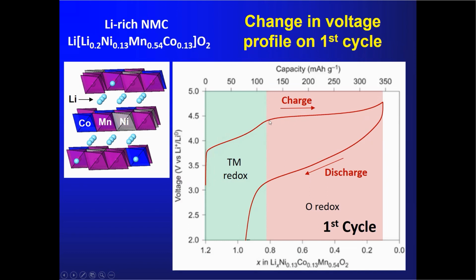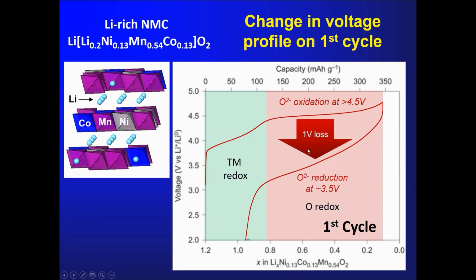But if you enter this higher capacity region, where you see this plateau, this is when we're starting to oxidize oxide ions. And now what you notice is that on the way back, on discharge, you have a large loss of voltage. And loss of voltage means, of course, loss of useful energy. So typically 1 volt, 1 electron volt is lost on the first cycle of this material. So you come back down here, you're getting out less than you put in. So once you start moving into the oxygen redox region, the chemistry, the physics of what's happening here is quite different from a transition metal center redox process.